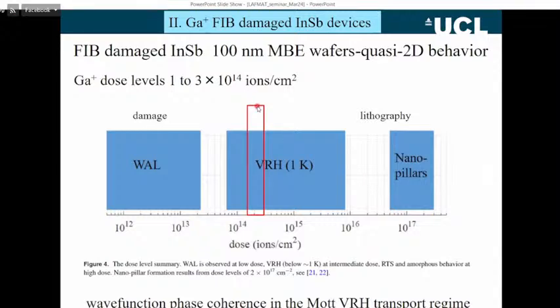And I'm just going to show you a set of devices where we've put disorder in this red rectangle here. So we're in this variable range hopping. As I say, if the disorder's too high, we can pattern the material. We're actually removing material, and you can get things like nanopillars. You can get quantum dots on nanopillars.